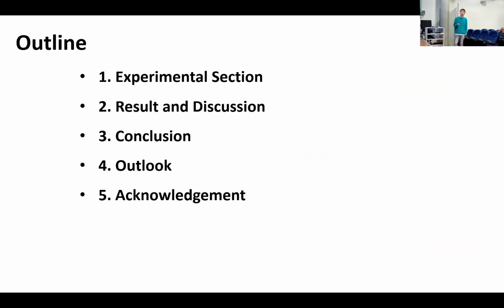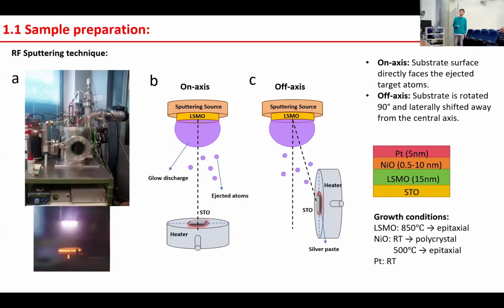So our outline is: first, I will give the experimental section, then the results and discussion, and then the conclusion, outlook, and finally the acknowledgement. So first, let me introduce the basic material preparation. We utilize the sputtering technique, where we apply a high voltage and the argon gas generates a glow discharge, and the argon ions bombard the target and eject the target atoms. So the target atoms then evaporate homogeneously onto the substrate.